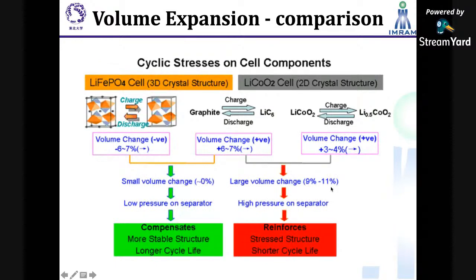This increasing volume puts high pressure on the separator, which is a porous membrane, and this creates stress in the cell and decreases the cell life in the case of lithium cobalt oxide. But in the case of lithium iron phosphate, this material does not have any phase or structural change, and it shows a negative volume expansion during lithium insertion and extraction.